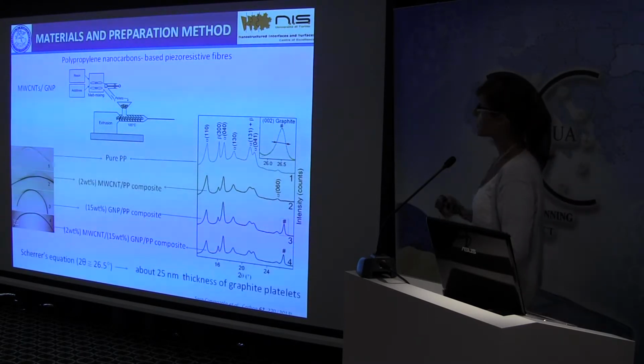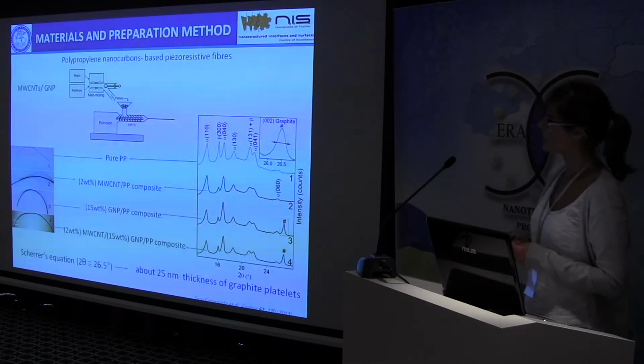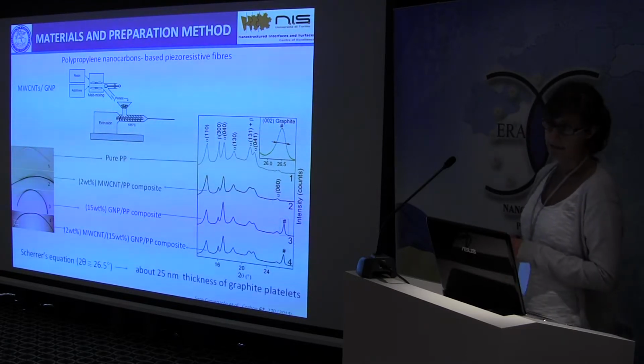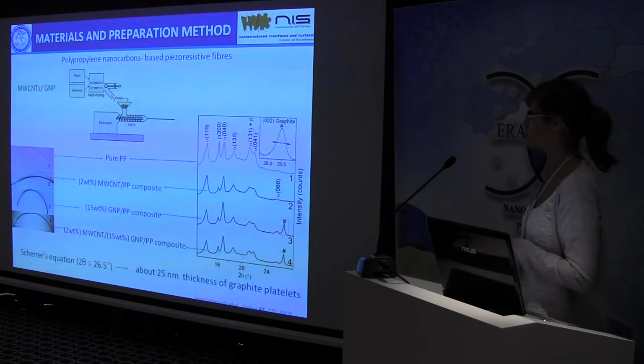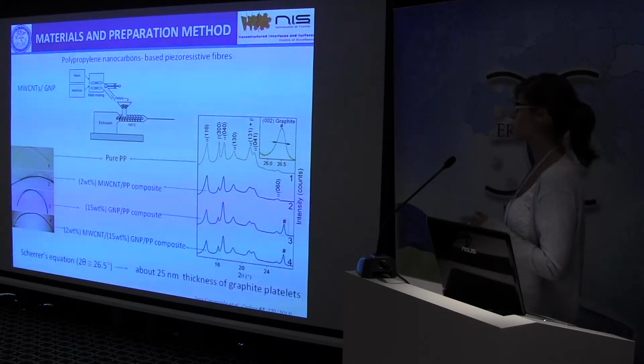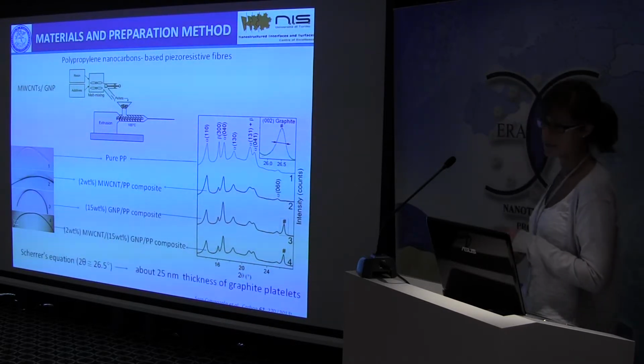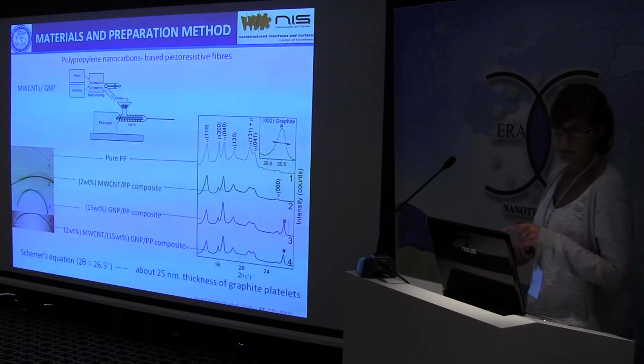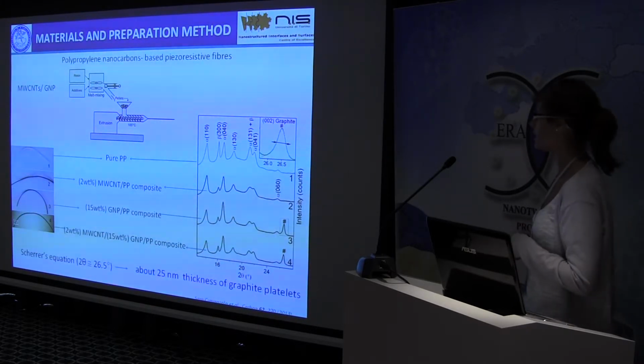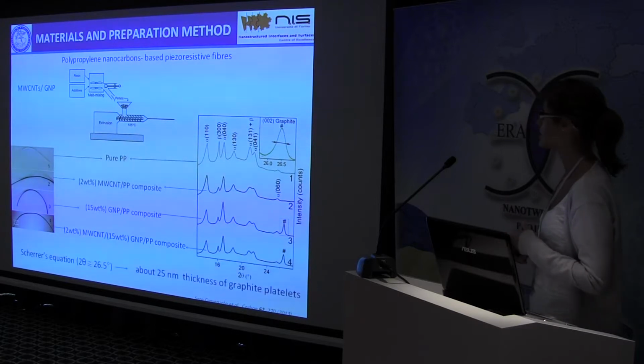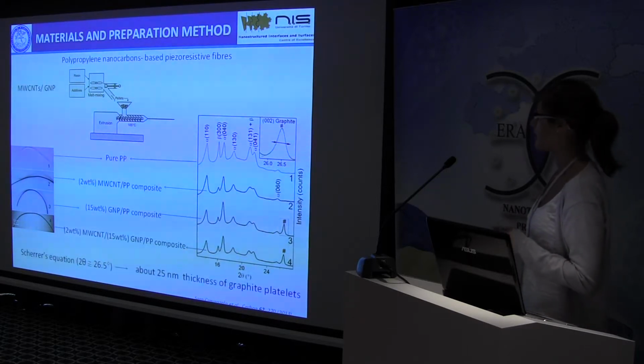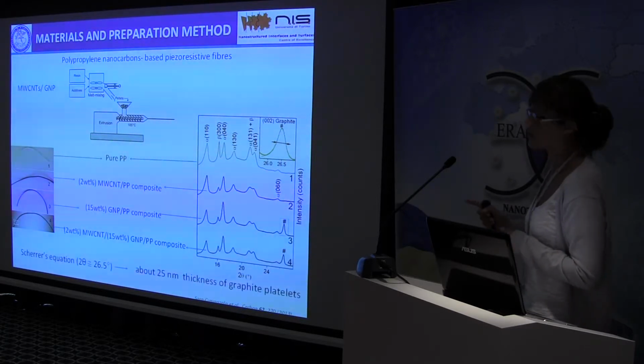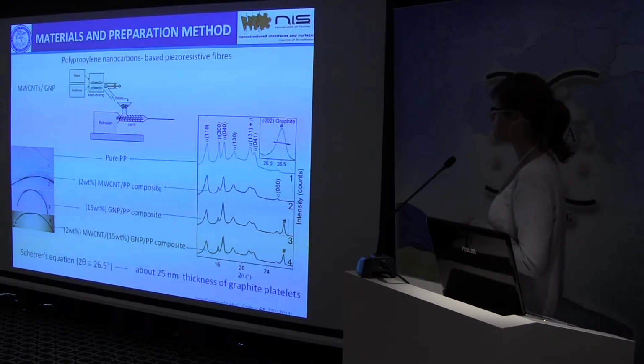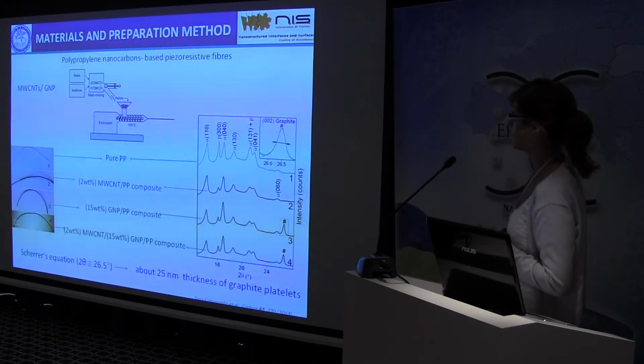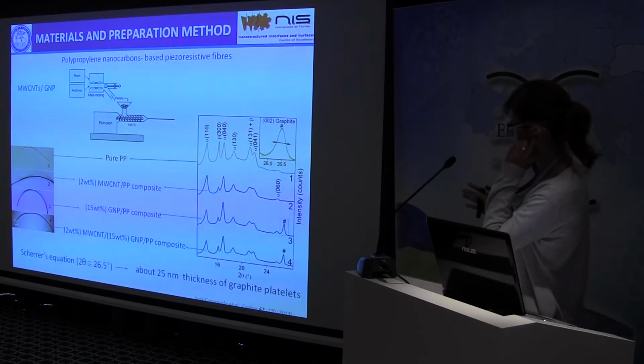In our composites, we use polypropylene as polymer matrix and multi-wall carbon nanotubes and/or graphite nanoplatelets as filler. To prepare the composite, we use the melt mixing method and then extrusion. And we realized the fibers that you can see in the picture. These fibers were characterized by X-ray diffraction, and here you can see the patterns.